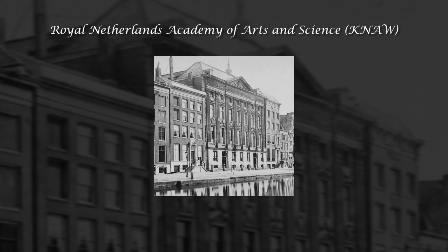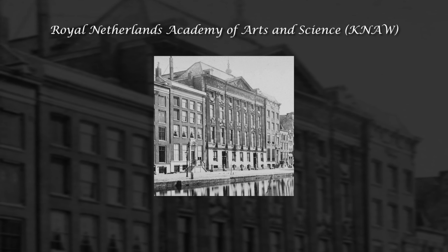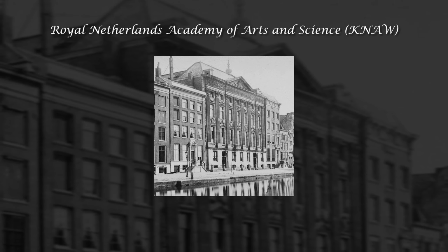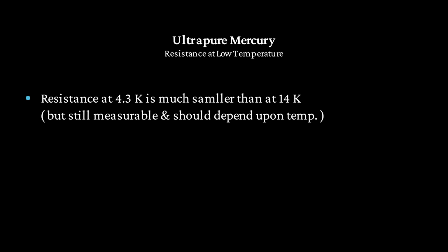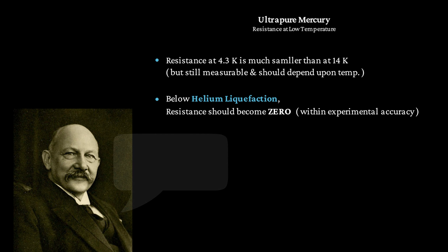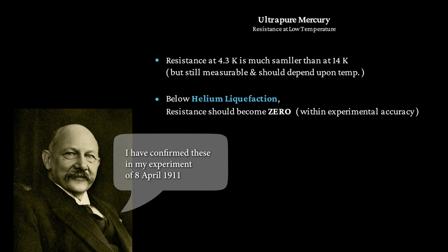Three weeks later, Onnes would report his results to the Royal Netherlands Academy of Arts and Science. His report would be as follows. For the ultra-pure mercury, the resistance at 4.3 kelvins is much smaller than at 14 kelvins, but still measurable with this equipment, and it should still be dependent upon temperature. For the very low temperatures below helium liquefaction, it should become zero within the limits of the experimental accuracy. He concluded that these have been confirmed by the experiment.